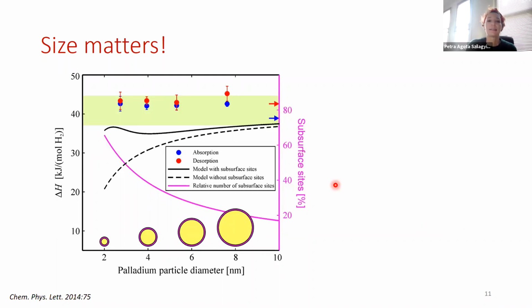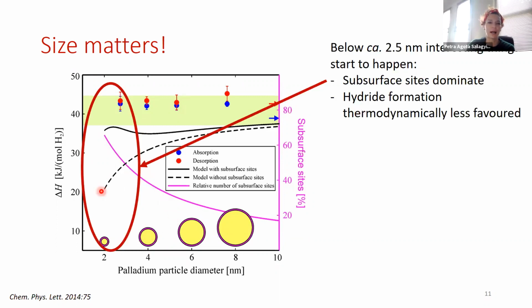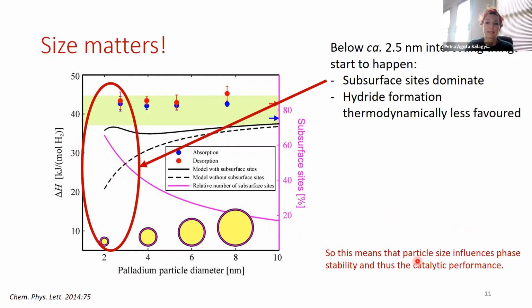Further to that, the stability of the interstitial hydride with respect to the metallic phase depends on the particle size. And as you can see here, just below about 2.5 nanometers, the interstitial hydride starts to be less stable when compared with the metallic phase for hydrogenation reactions. The hydrogenation or hydride formation. So it is quite logical to assume that at a certain size or below a certain size, the interstitial formation would no longer be thermodynamically favorable, and it would just simply not form. So this means that the particle size influences the phase stability and so the catalytic performance.